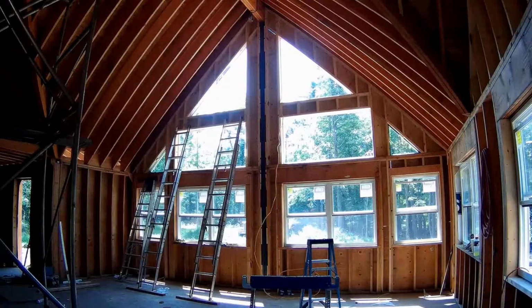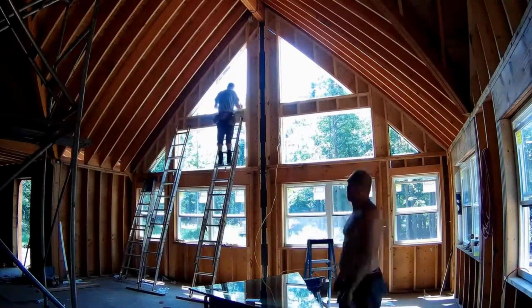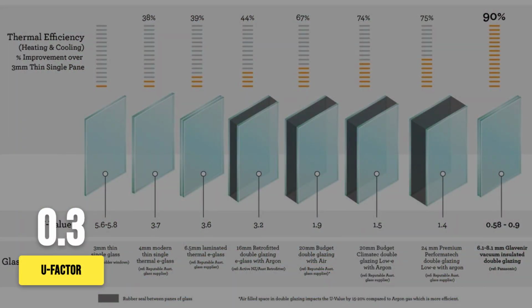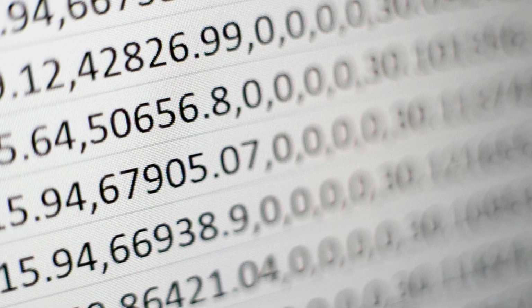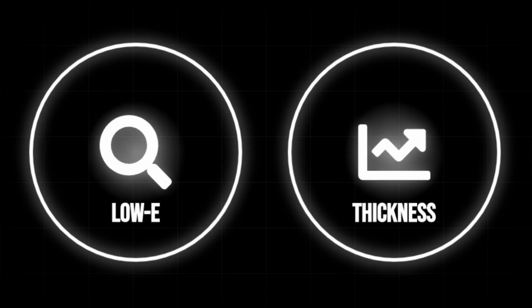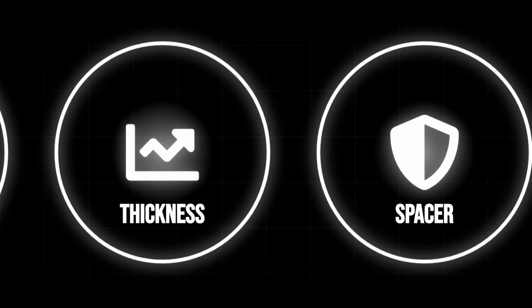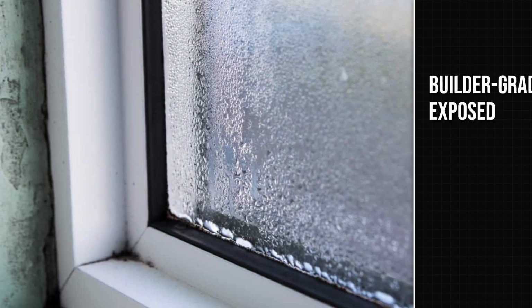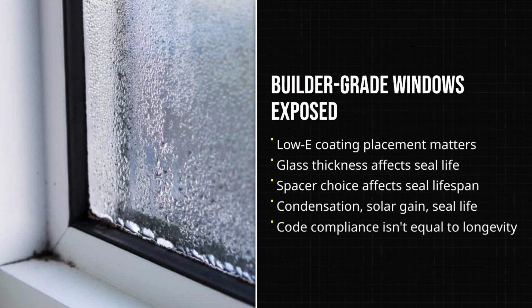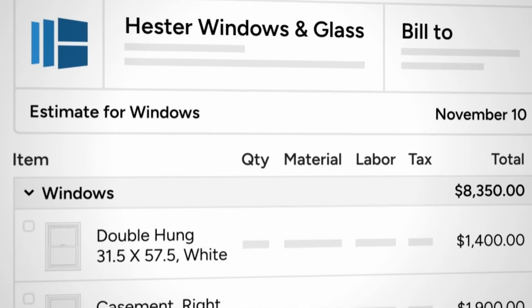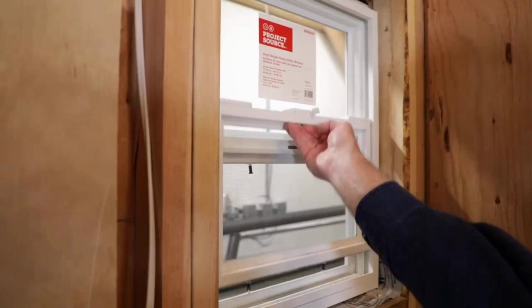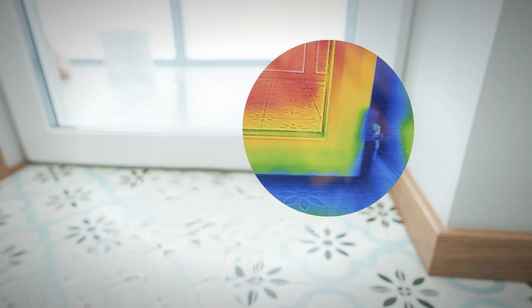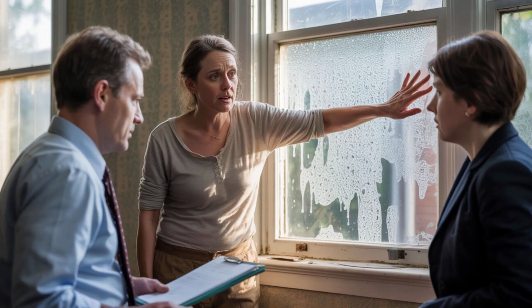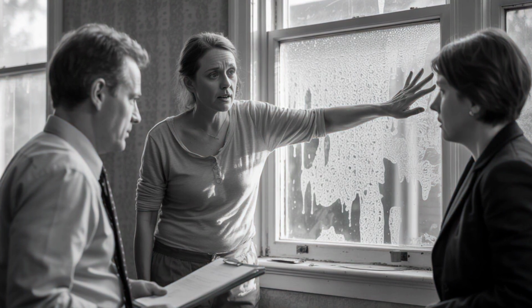Builder-grade windows are specified to meet the minimum U factor required by the energy code for the climate zone, typically 0.3 or below. What that number does not tell you is where the low E coating is placed on the glass, what thickness the glass is, or what spacer material sits between the panes. Those 3 variables control condensation resistance, solar heat gain, and long-term seal life. Volume builders choose the lowest cost glass package that passes the code inspection. You get a window that cleared a test. You do not get a window engineered for the 30-year performance your mortgage assumes.